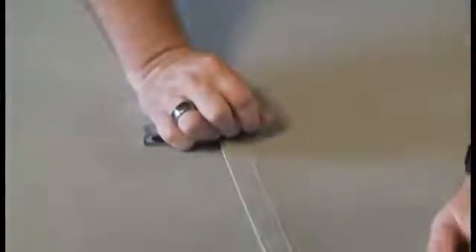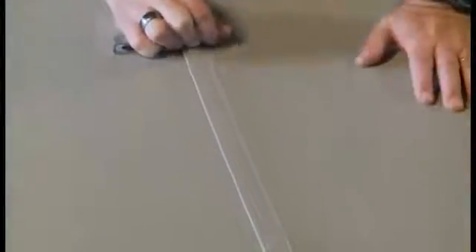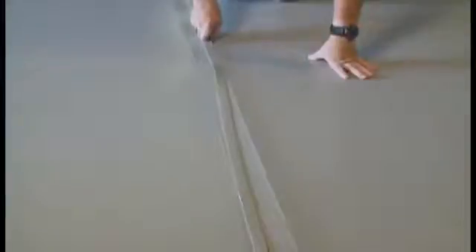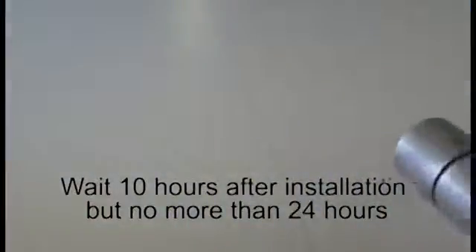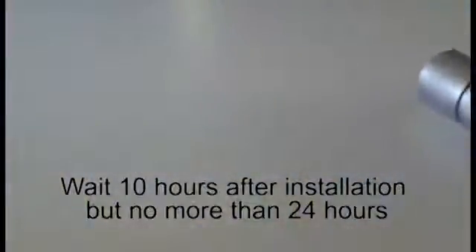Using your recessed scriber, scribe and cut the seam, leaving approximately a 64th inch gap in the seam. This will make it easier to groove the seam. Once the seam is cut, re-roll with a 100-pound roller. It is important to wait a minimum of 10 hours for the adhesive to dry prior to heat welding. Complete the heat welding within 24 hours of the installation.